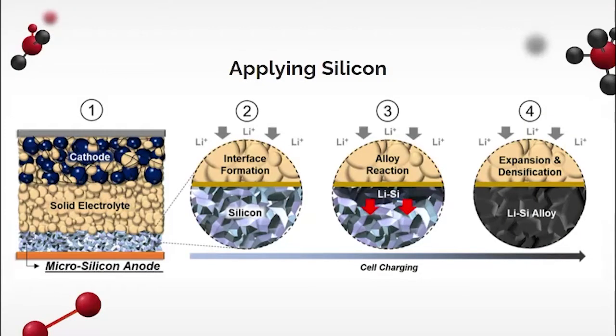UCSD aims to address grid energy storage issues and create cheaper, safer batteries by replacing graphite with silicon and a solid-state electrolyte. Firstly, when lithium ions sit between graphene sheets, the most thermodynamically stable configuration is 1 lithium to every 6 carbon atoms. For silicon, this is 4 lithium to 1 silicon atom, which is a theoretical increase of 10 times more storage capacity. Secondly, silicon is the second most abundant element within Earth's crust, making it more accessible and cheaper.